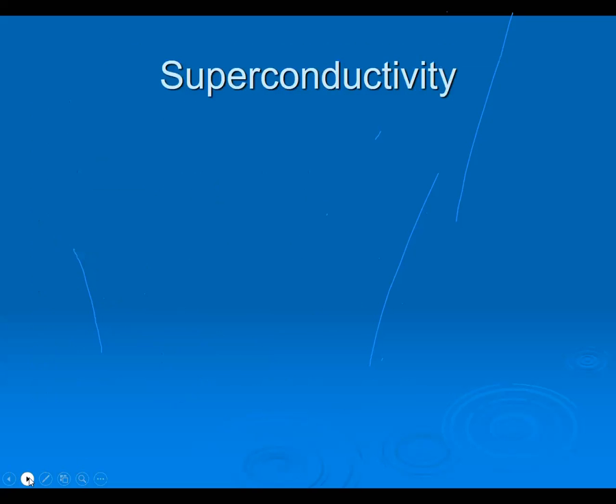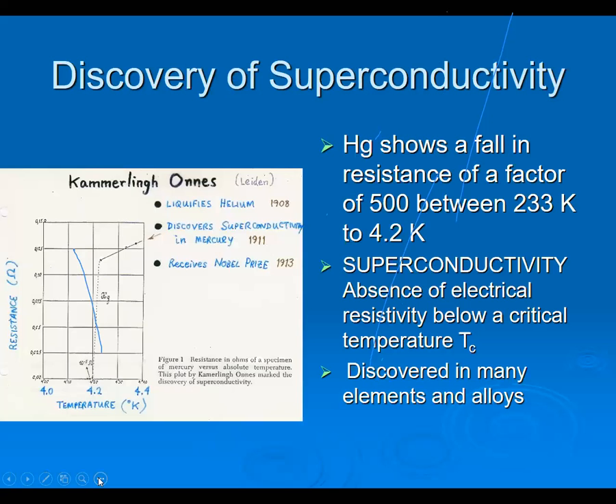I'll quickly go through. Finally, the most interesting, as I said, the best is the discovery of superconductivity, which was an unanticipated effect. This was by Kamerlingh Onnes. He had liquefied helium, and what he did was he was measuring the resistance of a specimen of mercury, and he found that there was a sudden drop of several orders of magnitude. Initially, he thought there was something wrong with the system, and you must be knowing the story, but this happened at a temperature of 4.2 Kelvin, as if it lost all its resistance and became a perfect conductor.